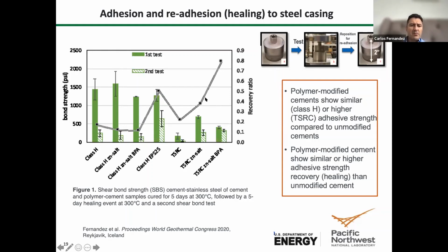This happened also with 2 of the polymers for the cement H, the zinc salt and the zinc salt with BPA. But for EPS 25, the original adhesive strength is statistically similar to the unmodified cement, but the recovery is significantly higher than the unmodified cement. In the case of TSRC, we start with a very low adhesive strength, but it's boosted if you add either of these 2 polymers, not EPS 25, but these other 2. And then you start with a higher adhesive strength, in some cases up to 3 times, but also the recovery ratio is much higher, and statistically different than the recovered adhesive strength of the unmodified cement.